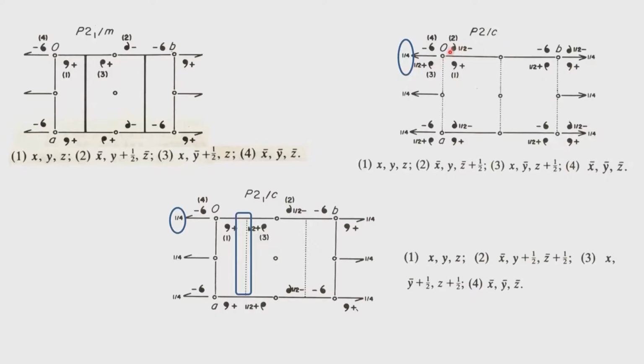So, these two positions therefore have a half translation in a direction which is perpendicular to this plane of operation, and therefore, it is not really perpendicular, it is along the C axis. So, we have to remember that in a monoclinic system the third axis is not at 90 degrees, right. So, this is now therefore going along the C axis, it is half translation along the C axis. Please remember, the half translation along the C axis will not involve a 90 degree angle, which is very important in monoclinic systems. So, it is moved by half the translation.